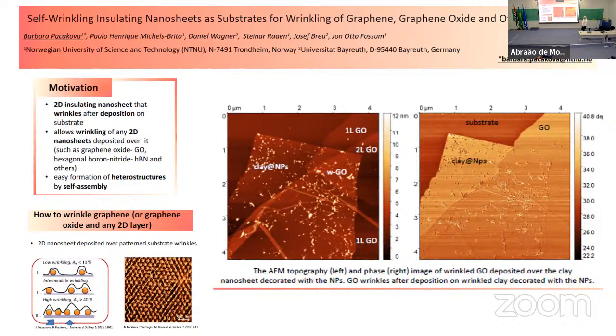The third poster we had at this meeting last week is on wrinkling. Wrinkling of nanolayers is important. For instance, if you use graphene or graphene oxide for detectors, gas detectors, the wrinkles are important. It's important that they are wrinkled. The wrinkles create hot spots for absorption on such materials. So what we can do with these clays, we can attach nanoparticles to the clays, put them on the substrate and control the wrinkling of the clay. On top of that, we can put graphene or graphene oxide, and in that way control the wrinkling of the graphene.